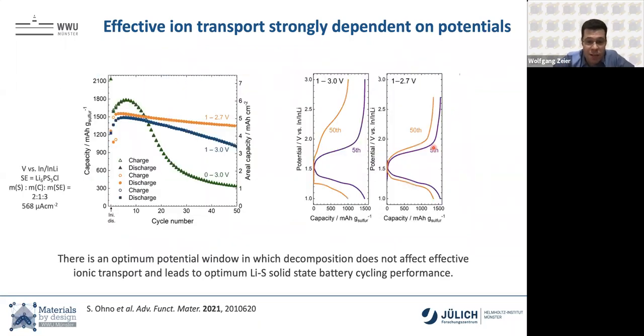Well, let's use that by changing the upper and lower cutoff voltage that we cycle our cells with. So if you cycle it entirely outside of the stability window, there's a lot happening and the cells crash really fast. But if you restrict it to this effective stability window, they run actually fairly well. And so you see that this overpotential evolution from here, as an example 5 to 50th cycle, is high if you run the cell way outside of the stability. If you run it within the stability, even though there's decomposition, it doesn't affect the performance. But you still have that large overpotential in between charge and discharge. So effective ion transport, just because it doesn't get worse, doesn't mean that it's good enough for good cells.